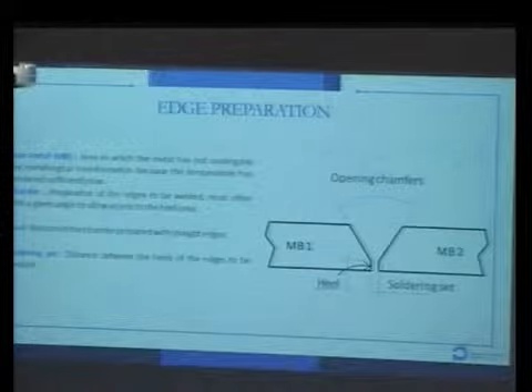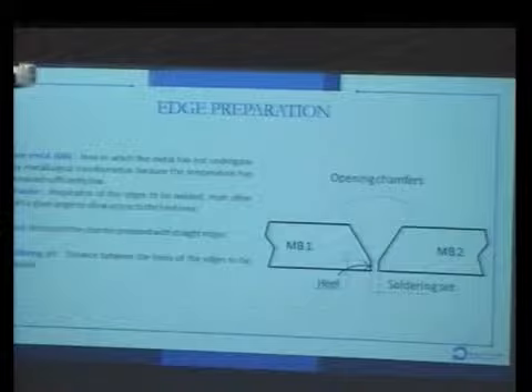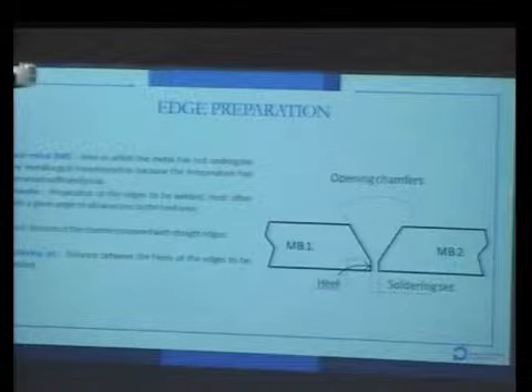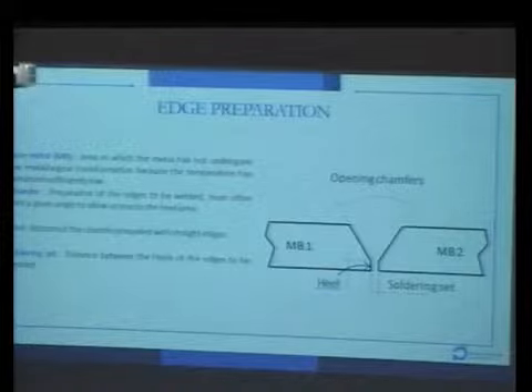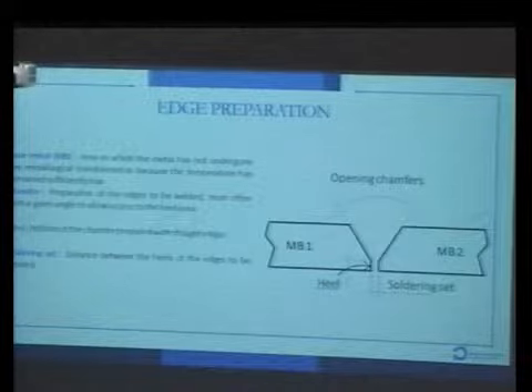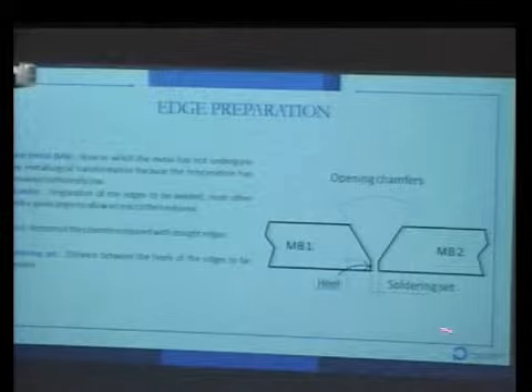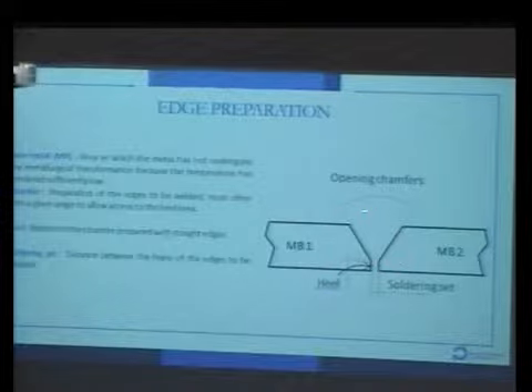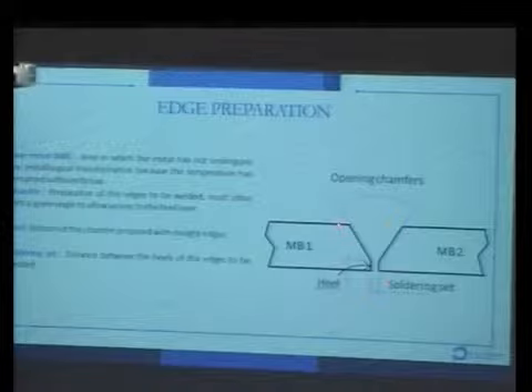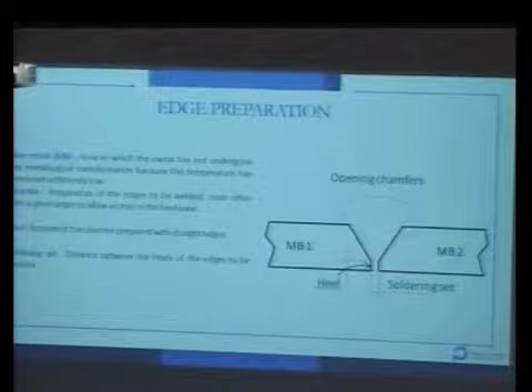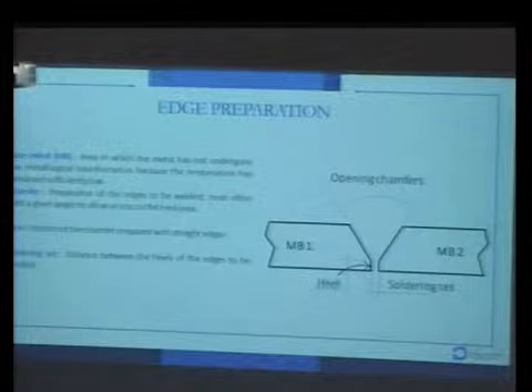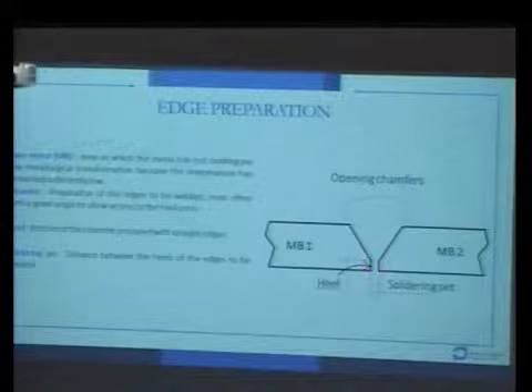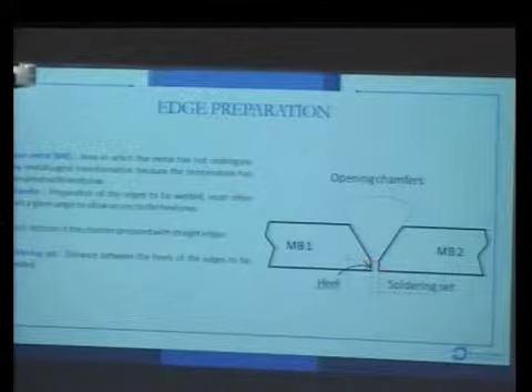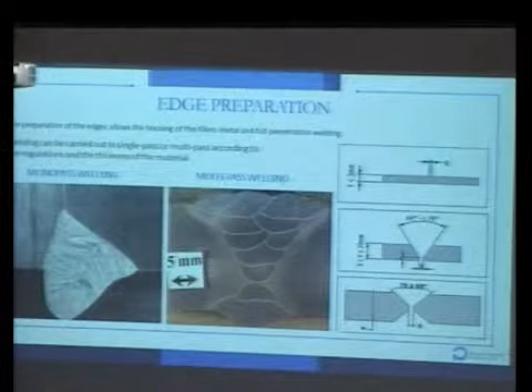For example, when you weld base metal 1 and base metal 2, if you take a big thickness, more than 3-4 millimeters, I say big, but it's not big, you want to have here a laser point. You want to have here a liquid metal. If you take all this metal liquid with all this thickness, it will be very heavy. And too heavy, it will fall and you will make a hole. So you have to prepare here with a chamfer here. You have to prepare. We want to make one root weld, and then we have to make more welds.